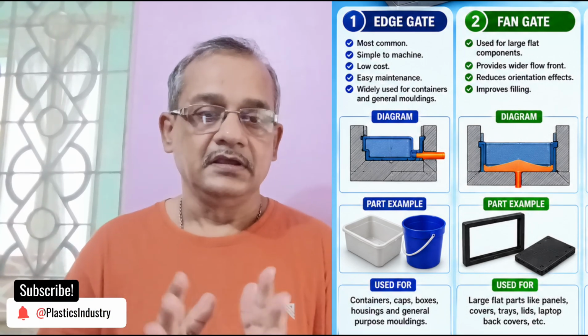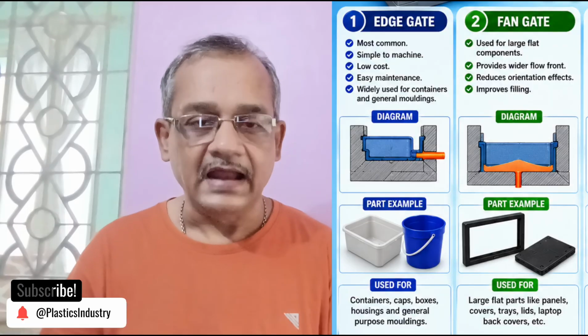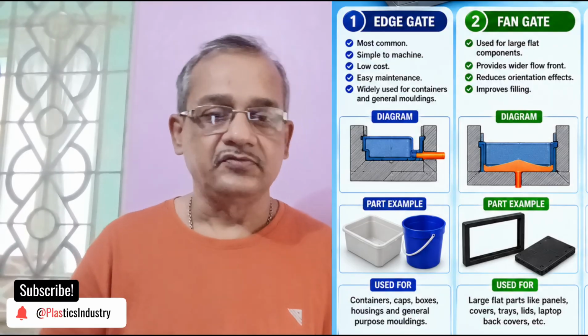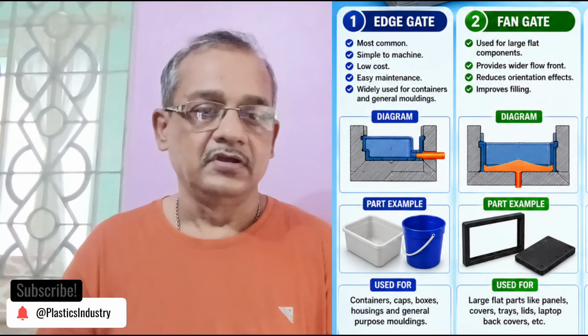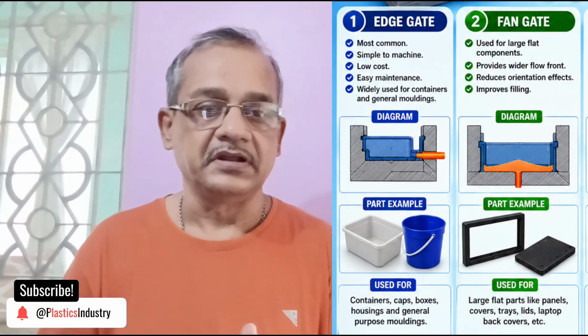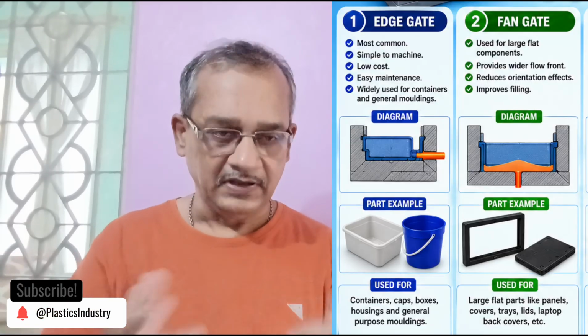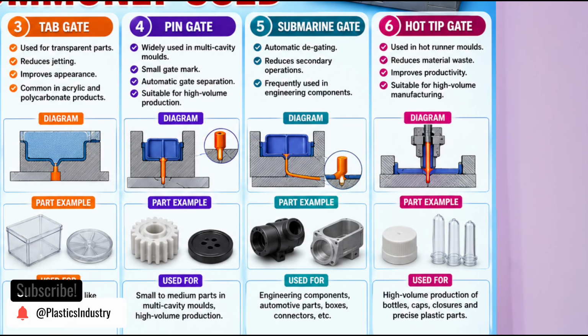Fan gate, used for large flat components, provides wider flow front, reduces orientation effects, improves filling. Tab gate, used for transparent parts, reduces jetting effect, improves appearance. Common in acrylic and polycarbonate products.